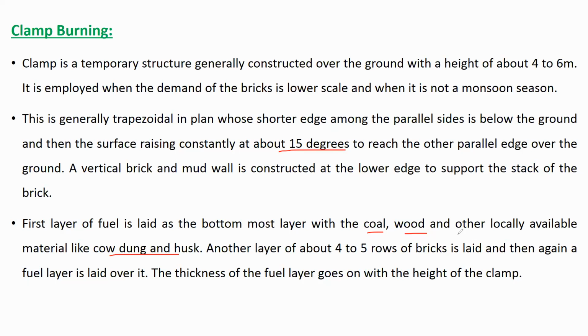4 to 5 rows of bricks, again fuel layer, again 4 to 5 rows of bricks, again fuel. Okay, so like that you have to keep on increasing the height. And height should be maximum 4 to 6 meters, not more than that. Okay, 4 to 6 meters is maximum height.